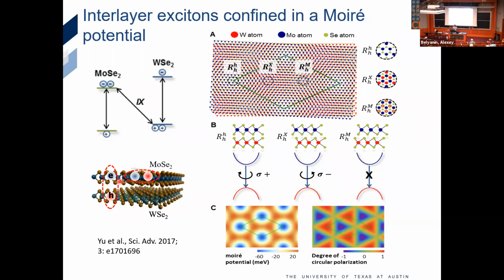I showed one way of creating a Moiré superlattice, which is the energy band modulation. You can actually have a structure with minimal energy modulation, but the dielectric constant variation is another way to create a Moiré superlattice. So it depends on the structure. They probably still follow this period, but you do need to take into account the dielectric constant variations as the full picture for the Moiré potential.